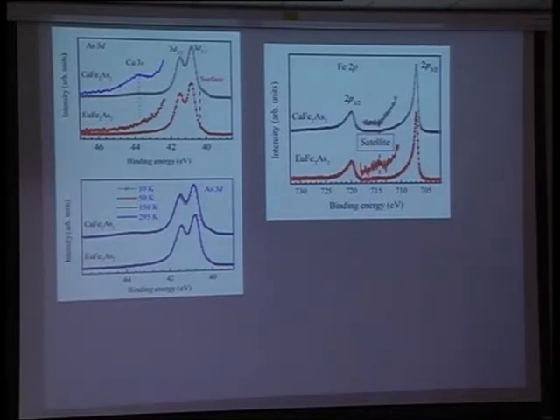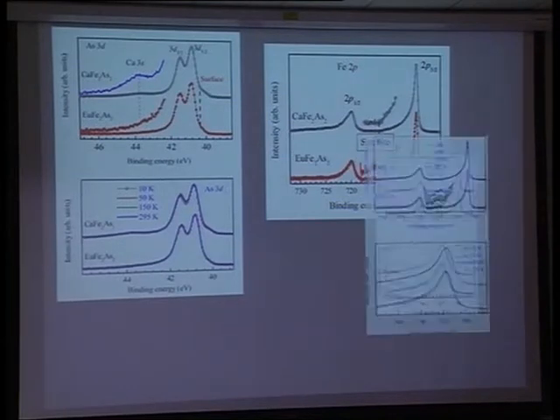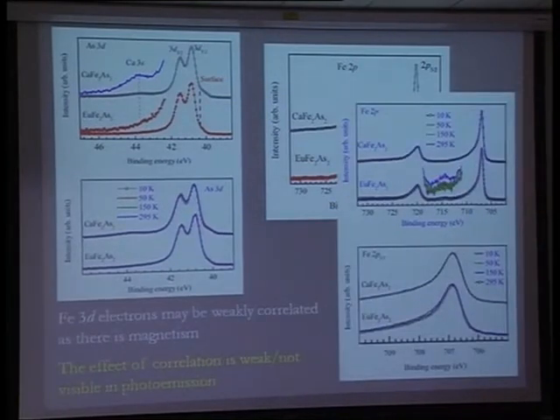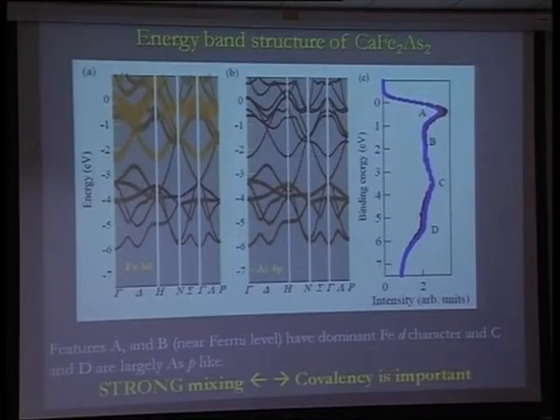So in calcium iron 2, arsenic 2, you can see that it's typical like iron metal, there is no signature of satellite which is seen. If you change temperature, then you also see, as we have shown by expanding this region, that absolutely no change with temperature. So what one can conclude from this is that, whatever has been theoretically predicted, the electron correlation is not so strong in these materials.